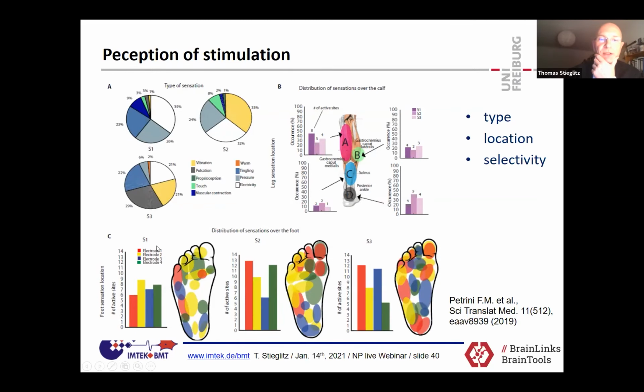What I want to show you here is that the different colors code for different implants. So we had again 4 implants in branches of the sciatic nerve. And 1 electrode means this is 1 implant with up to 14 contact sites. And here, if we stay with red, in patient 1, S1, we had 6 sites that were able to elicit meaningful sensation. In the other patient, we had 13. In the third patient, we had about 12.